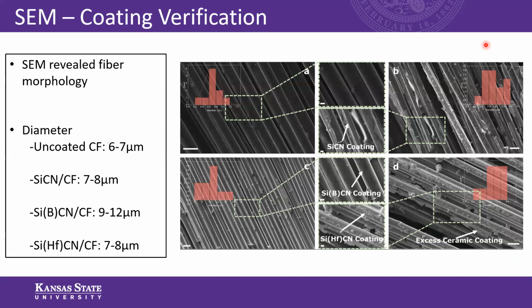Now, before testing, some SEM images were taken, mainly to verify the coating. And the SEM images revealed the fiber morphology for each case. And we started out with uncoated or neat carbon fiber. These fibers had an average fiber diameter ranging from 6 to 7 micrometers. Then some images of SiCN coated fibers were taken, and the fiber diameter did increase to a range of 7 to 8 micrometers on average.